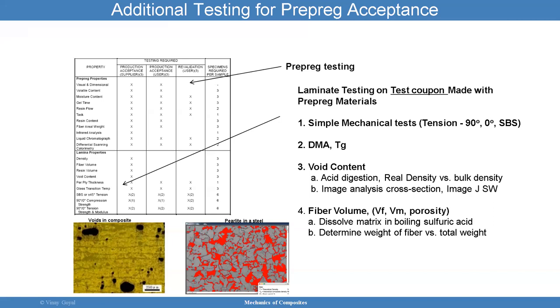In a DMA, what we normally do, we apply a sinusoidal variation of stress to the sample, and then we monitor the resulting deformation. So it's a mechanical test. That's why it's called a dynamic mechanical analyzer. And usually you apply like 1 hertz of applied loading, and the strain is typically kept constant, and the temperature is increased. We increase this at a constant heating rate. Okay, so we increase that, and then we're able to determine how much damping or how much loss we have in the system when this is done. And we're measuring here the storage modulus, or basically we want to understand the Tg.